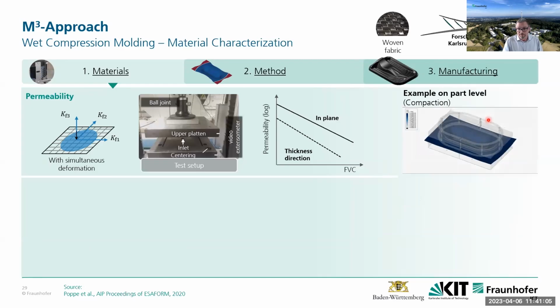Another important material aspect is interaction between permeability and compaction. Permeability is determined via a one-dimensional flow according to Darcy's law. A gap is approached, we have a constant volume flow which is set, and then we measure the pressure difference stationary. In-plane is self-measured, even for sheared samples we need to measure that and determine, and through-thickness, that's something we did externally with Fraunhofer colleagues in Augsburg.